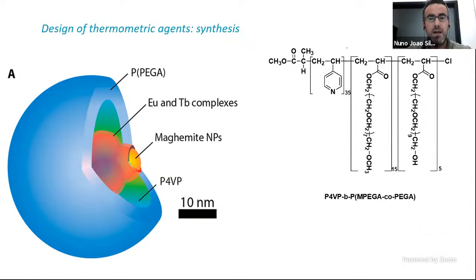So the synthesis. So your chemistry, you're probably wondering, how do you do that? How do you synthesize this? So basically, it's a core shell nanoparticle. It's a core shell system. In the core, you have these magnetic nanoparticles that, in this case here, are behaving as local heaters, as heat spots. And on the top of this maghemite, you have a polymer. The key point here was the development of this block polymer, which has these pyridine groups here, and these pyridine groups have a preferential interaction with the surface of the iron oxide. And in these polymer chains, you can incorporate these europium and terbium complexes that give you the information about temperature with their fluorescence. So this is basically what you're doing.